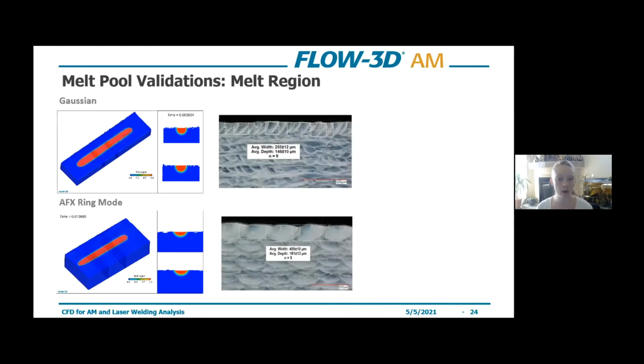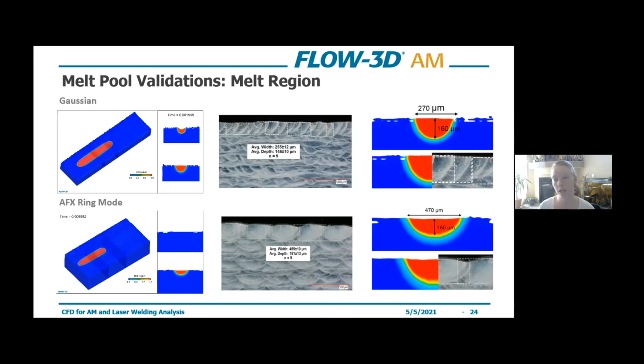So in setting up these simulations, of course, you always have to start with a validation. So we ran simulations for the Gaussian distribution and the AFX ring mode. Econity provided us with cut cross sections from their experiments so that we could compare the width and depth with simulation and experiment. And then in doing that comparison, we can see that there is good agreement between the Flow3D AM simulations and the experiments provided by Econity.